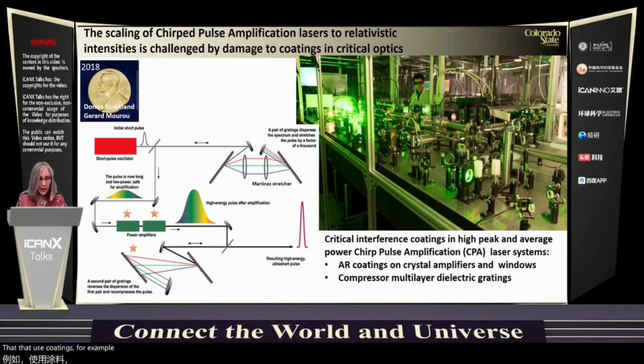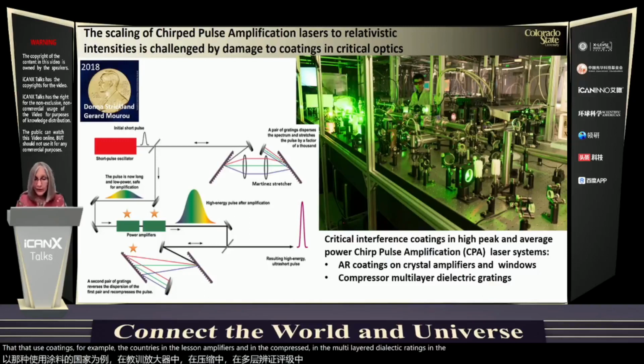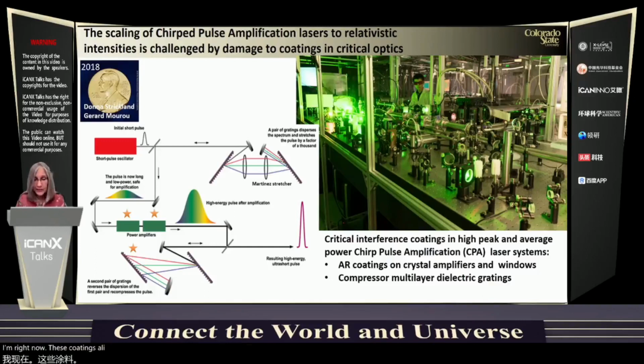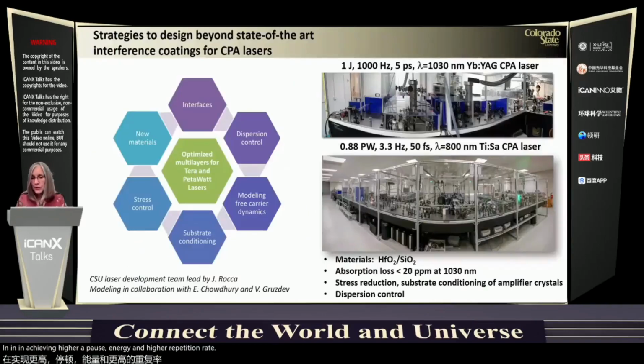Now, there are critical components in this chirped pulse amplification system that use coatings. For example, the coatings in the laser amplifiers and in the multi-layer dielectric gratings in the compressor. And right now, these coatings are a limiting factor in achieving higher pulse energy and higher repetition rate. So our efforts combine theory and experiments, and are directed towards improving the performance of the anti-reflection coatings in the amplifier crystals and other critical components for two particular lasers that are being developed at Colorado State University by Jorge Rocca and colleagues.